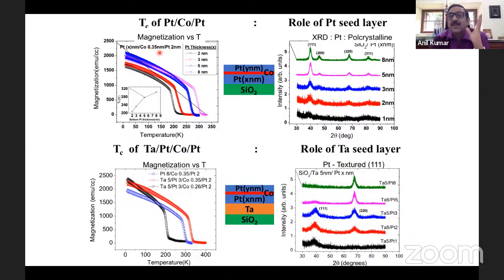You see here, I'm having only 0.35 nanometers of cobalt layer. If I vary the platinum layer thickness between 2 nanometers to 8 nanometers and plot the magnetization, this is a SQUID magnetometer measurement, magnetization versus temperature, you see that the TC of the material goes above room temperature when I have 8 nanometers of platinum. Whereas if I add a tantalum layer below this platinum layer, I can increase the TC: with just 3 nanometers of platinum and 0.35 nanometers of cobalt, the TC is above room temperature. But if I go even to 0.26 nanometers of cobalt, you still see ferromagnetism, whereas the TC is below room temperature.